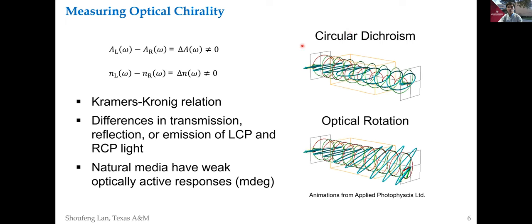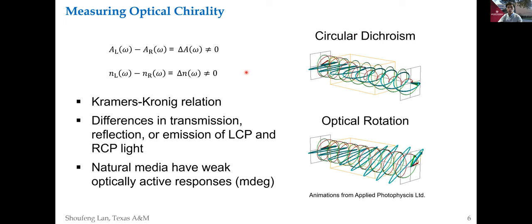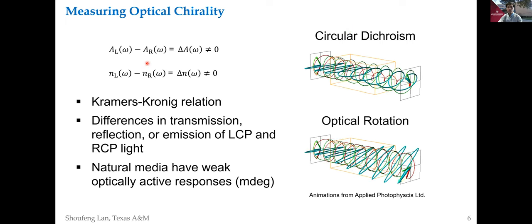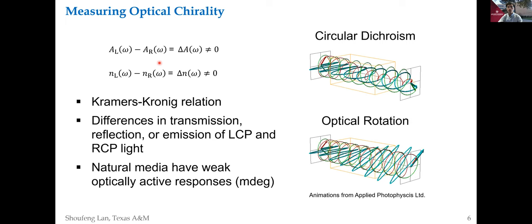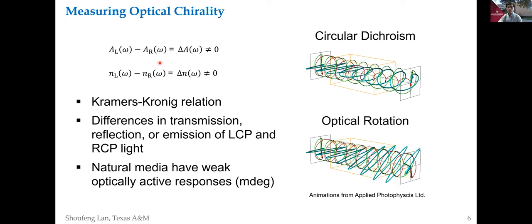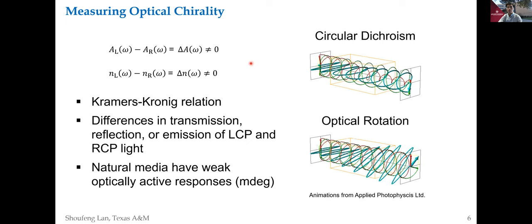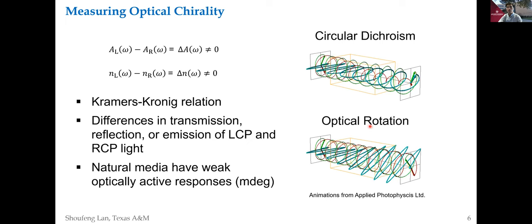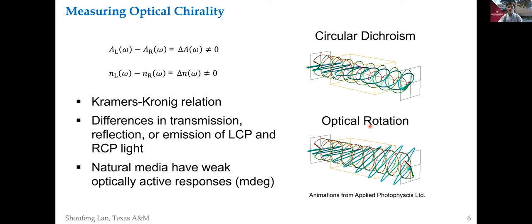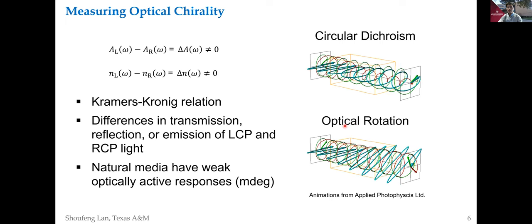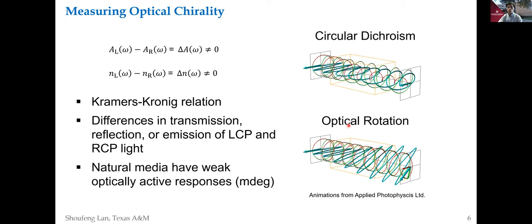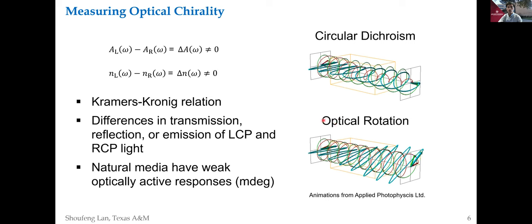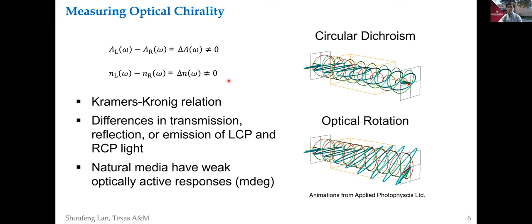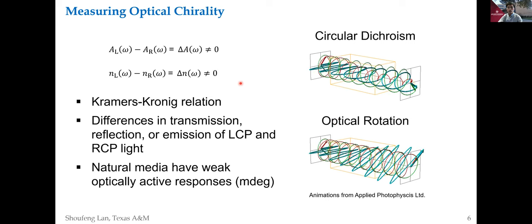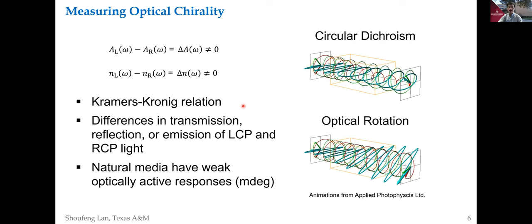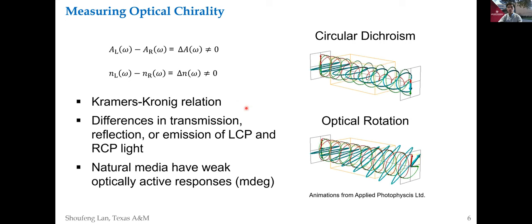For circular dichroism, the absorption of the LCP and RCP light will be different, which corresponds to the imaginary part of the refractive index. But for optical rotation, when you shine a light on the chiral medium, the linear polarization will rotate by an angle, which corresponds to the real part of the refractive index. So circular dichroism and optical rotation are related by the Kramers-Kronig relation.